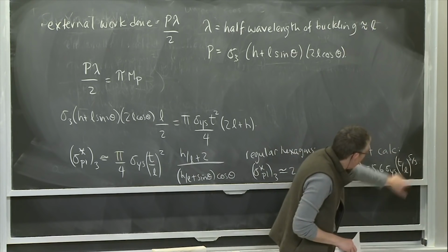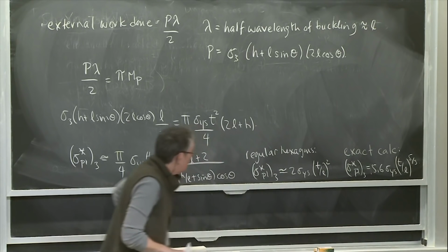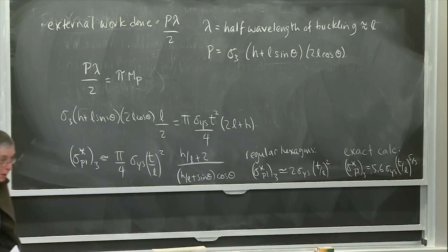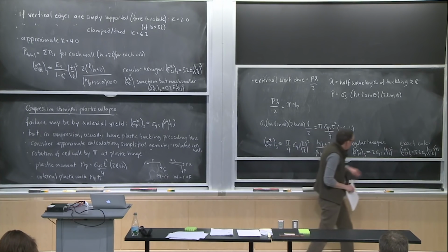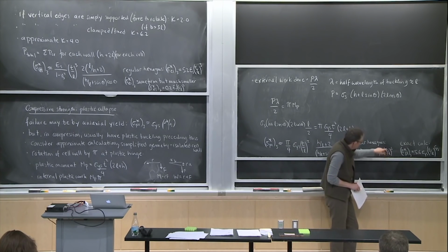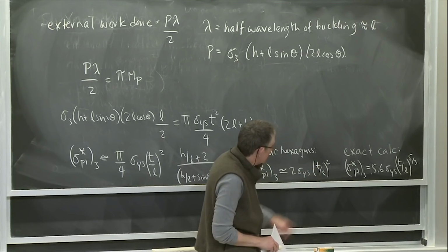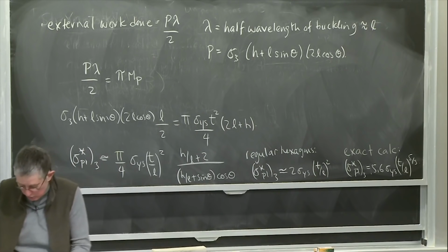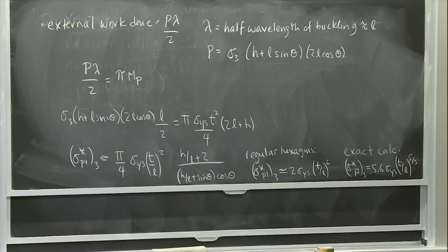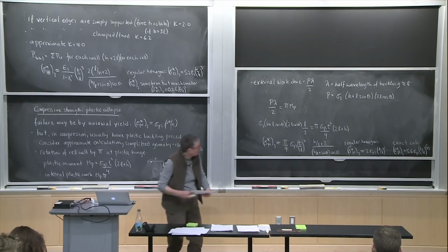So this power here, 5/3, is a little less than 2. And that's because of the additional constraint of the neighboring cell walls. But the main thing we're interested in with these sorts of calculations is the power dependence on the density. And this simple calculation, obviously it's not exact, but it gets you close.